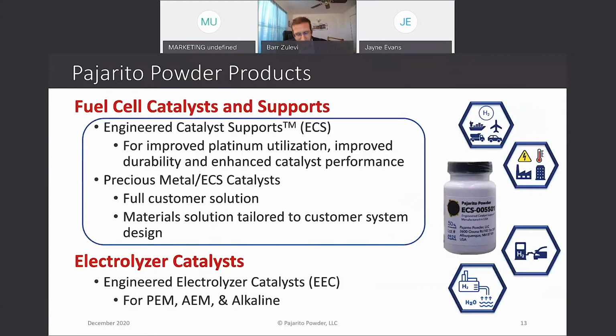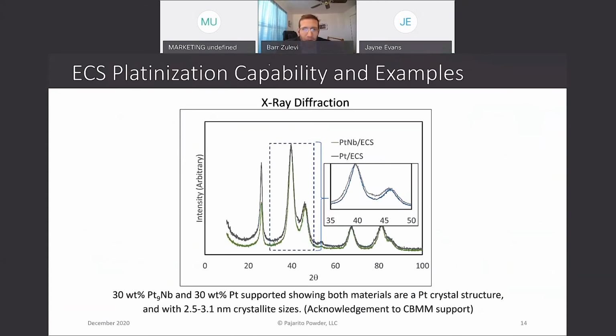So now that I've described a little bit about the supports, let's look at the actual fully catalyzed systems. And here what we see is a full catalyst, platinum on ECS, as a baseline, as well as a platinum 3 niobium 1 alloy that we created with these materials. You can see here they're nicely distributed, 2.5 to 3 nanometer crystals.